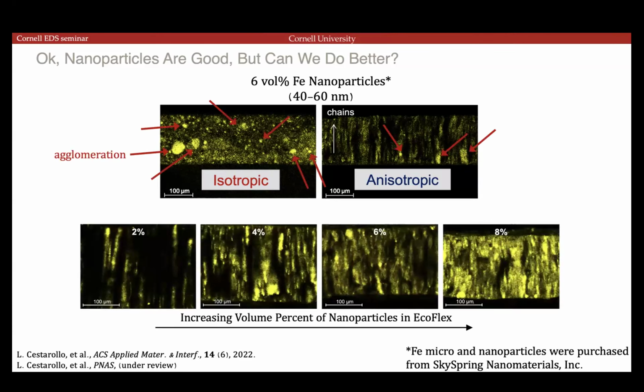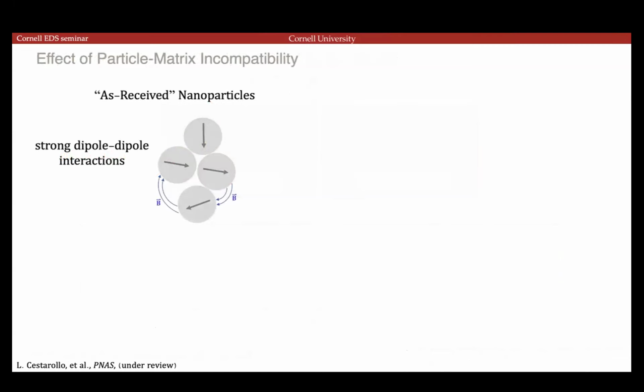But what you find is if you increase the nanoparticle concentration in the films, that agglomeration just dramatically increases. And so the best way to improve this is by somehow making particles that are not so strongly interacting with each other.